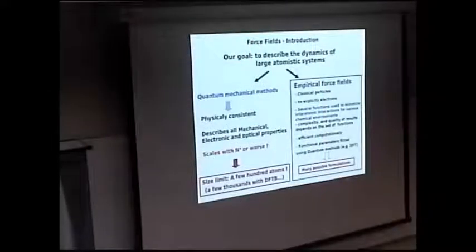These functions must be chosen with some care, because they should change the behavior depending on the chemical environment that the atom is in. The complexity and the quality of the results will depend on this set of functions, but this kind of approach is computationally efficient. The functional parameters can usually also be fitted using quantum methods, typically DFT. Then we have many possible formulations, and I will talk a little bit about this.